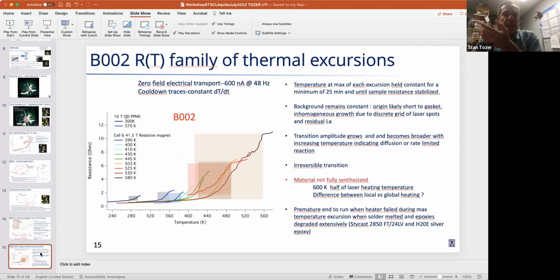What I've done in this final slide of these thermal excursions is to show how we moved out. Not only does the amplitude increase as we go through these thermal excursions, but also the transition width. And in fact, at about 500 degrees Kelvin, the yellow trace, we really start to see a broadening of the transition, with many phases coming into play. And I suspect that has to have something to do with either diffusion rate or activation of the release of the hydrogen, or incorporation of this other material that's making this interesting 556 Kelvin superconductor.